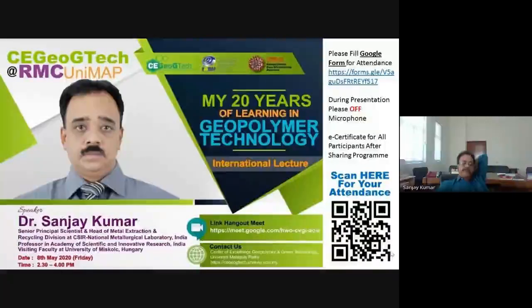See, the main cost of a geopolymer comes from the chemical part. So we try to reduce the chemical part by adding some reactive material in the geopolymer composition, something which is very amorphous in nature. Then the requirement of chemical becomes low. So that is one possibility. Another possibility is, when we use mechanical activation, reactivity improves, so the requirement of chemical comes down. So these two approaches we have used.